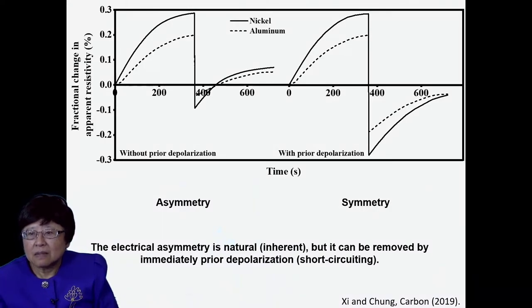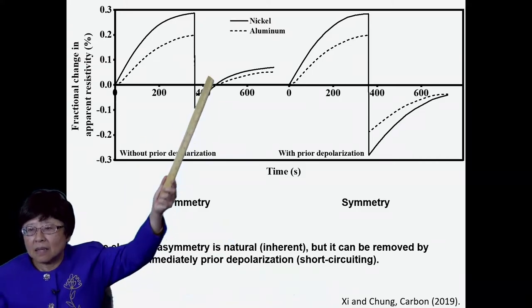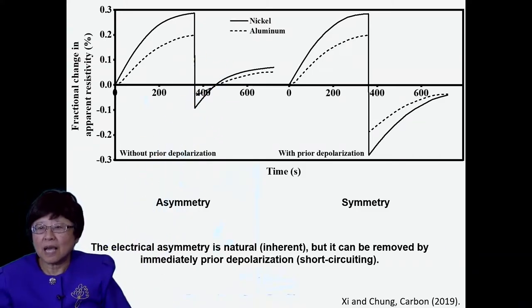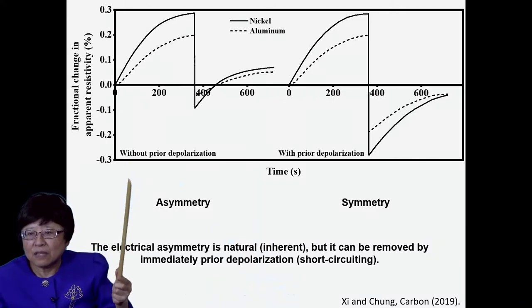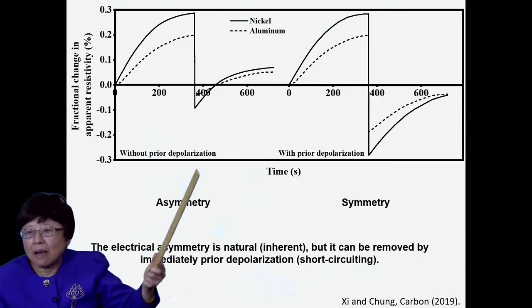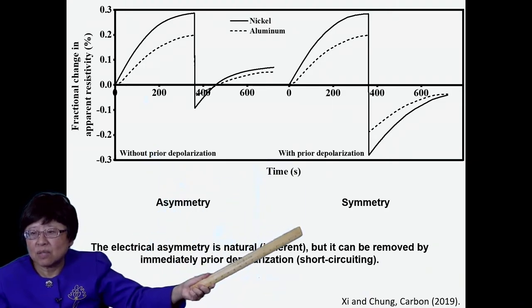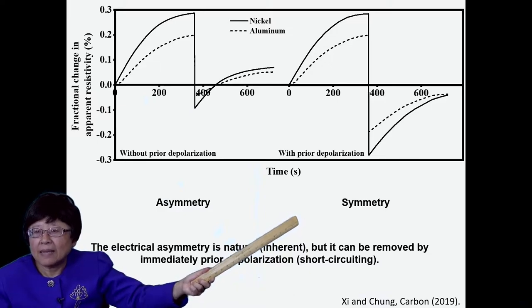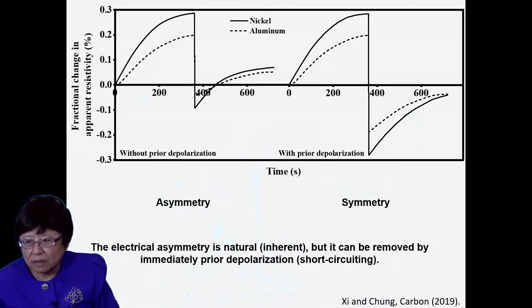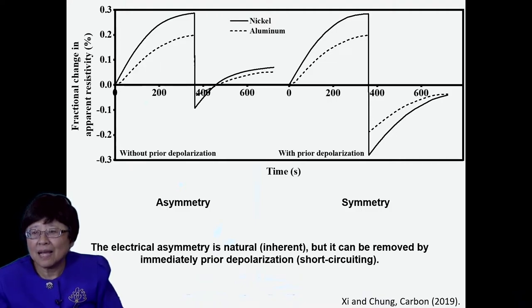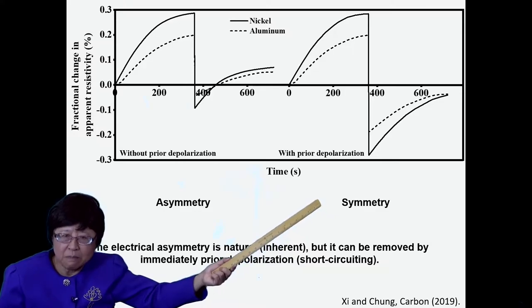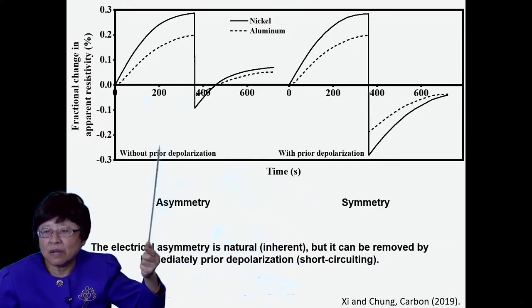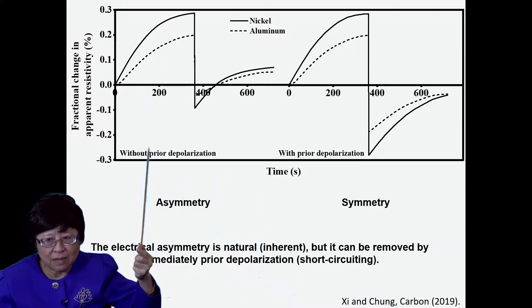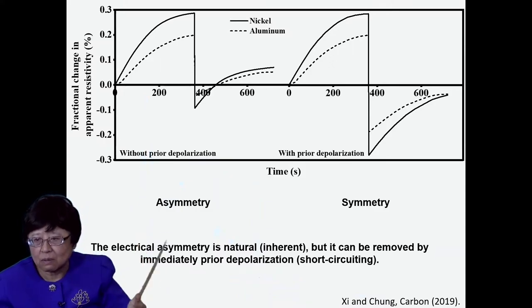These are real data for nickel in solid curve and aluminum for dashed curve. And the left here shows asymmetry as obtained naturally. But the right shows symmetry as obtained by short-circuiting the material for 6 minutes immediately before testing. So unless one does that brute force short-circuiting immediately before the testing, the material exhibits electrical asymmetry, and that's inherent, that's natural.